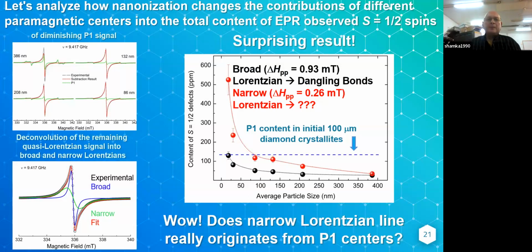Okay, let's analyze how nanonization changes the contribution of different paramagnetic centers into the total content of EPR observed spins. We did a very simple thing. We just subtracted the P1 signal from the experimental signals for different concentrations. What remains is only these lines, and this line was deconvoluted into two Lorentzian signals. One is broad, which is attributed to dangling bonds, and a narrow one of unknown nature.